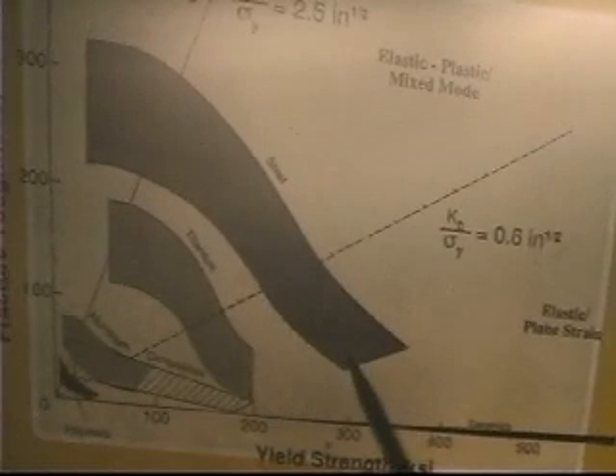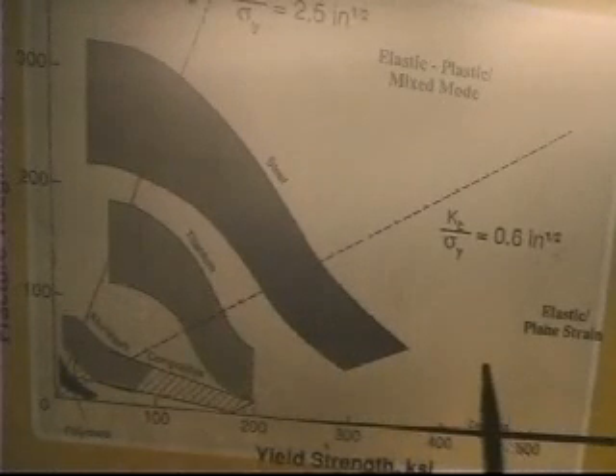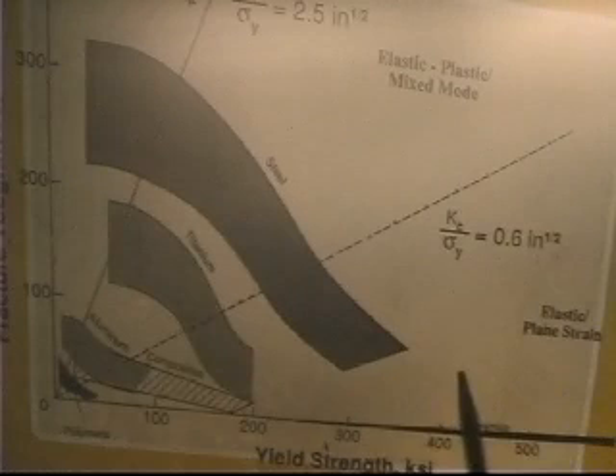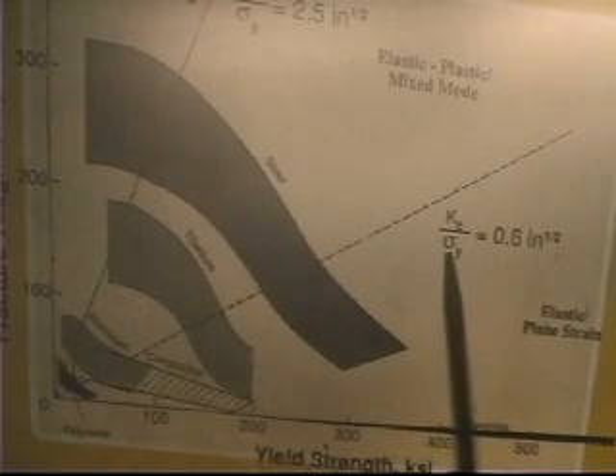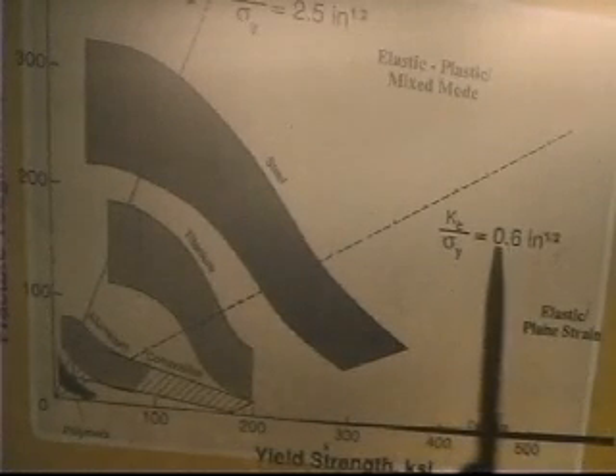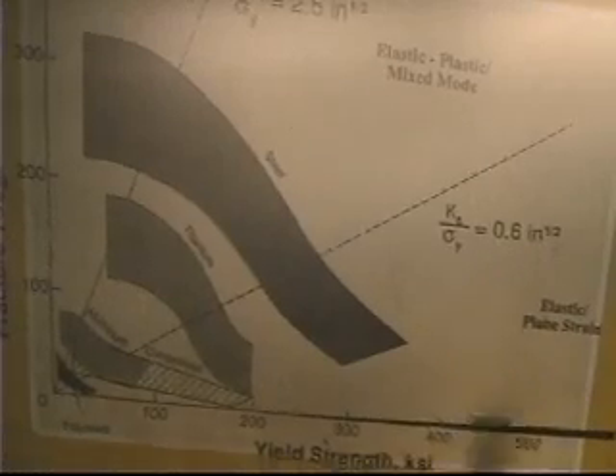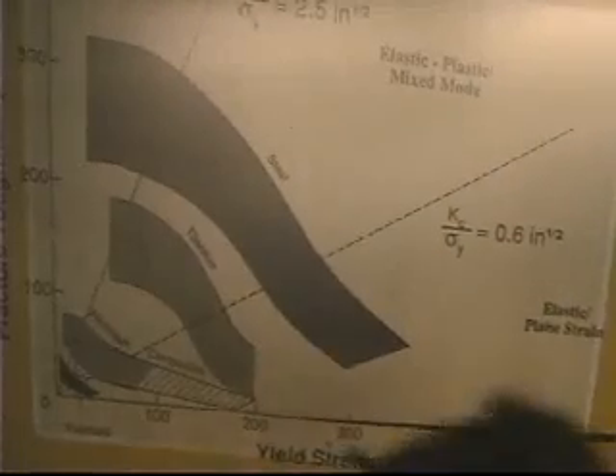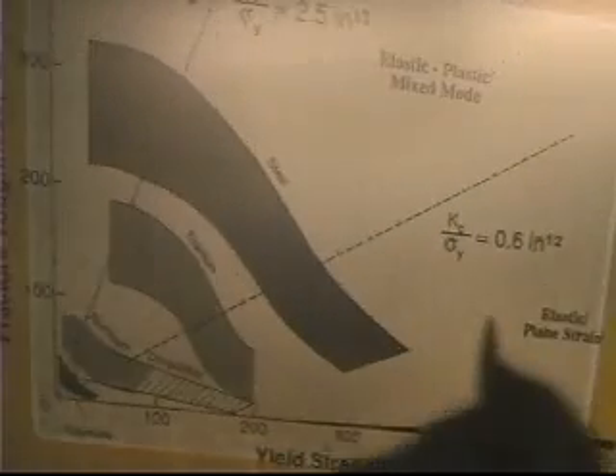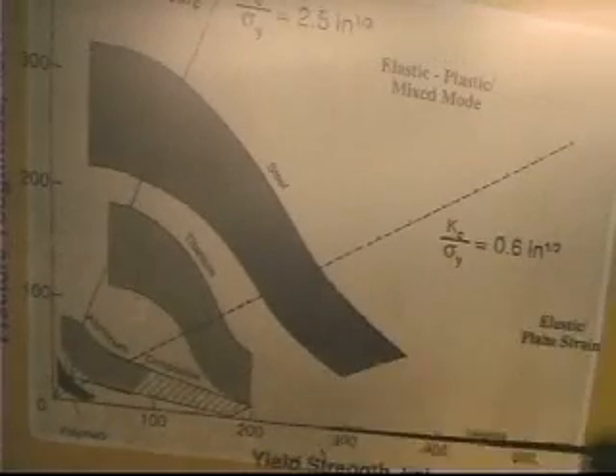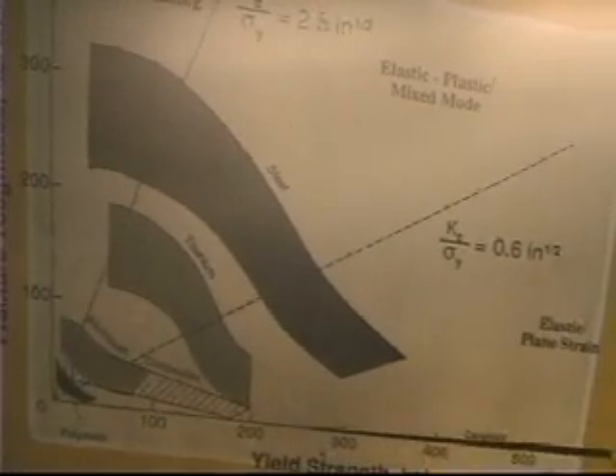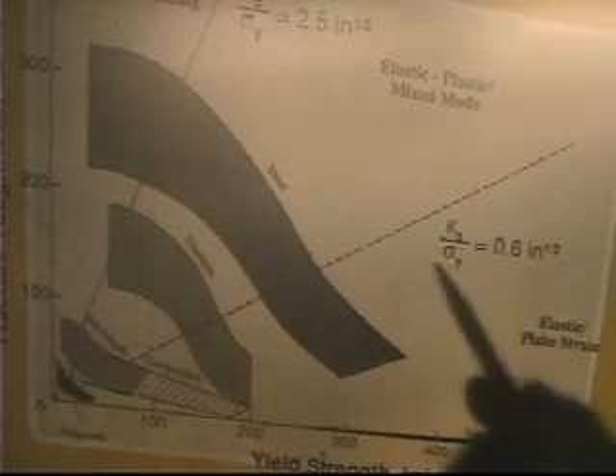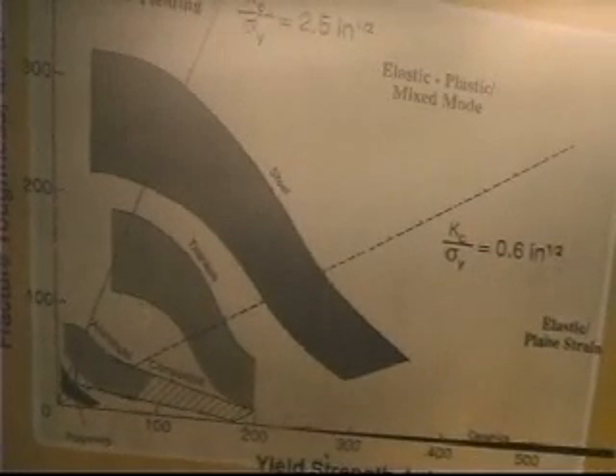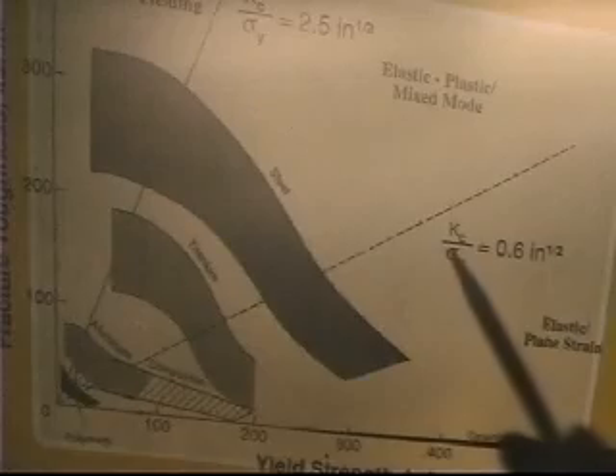Over here, you're getting to brittle materials. Not much toughness, a lot of strength, and therefore they're going to crack on you. This fracture toughness divided by yield strength, when it's less than 0.6 inches to the 1/2, that's supposed to be squared. Sorry, no, it's not squared. Actually, take it back. No, that's correct. Kc over sigma y is 0.6 inches to the 1/2. So the plot's correct. Sometimes we plot this whole quantity squared, and so that would be in inches rather than square root of inches. But anyway, if it's greater than 2.5, then you've got great plastic yielding.